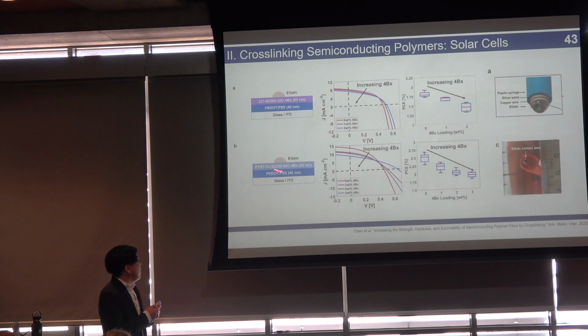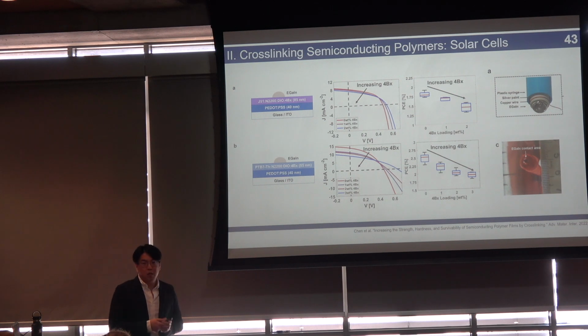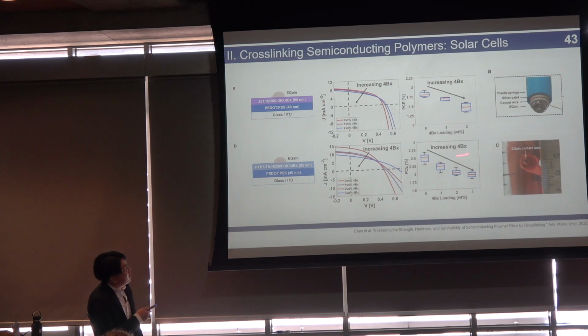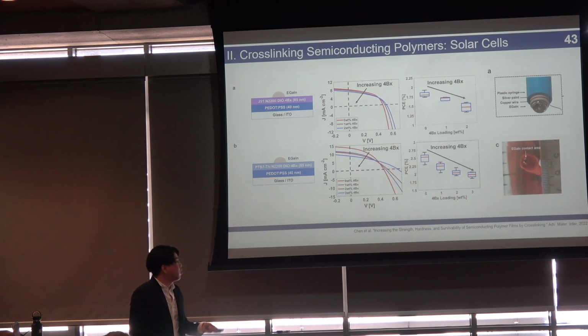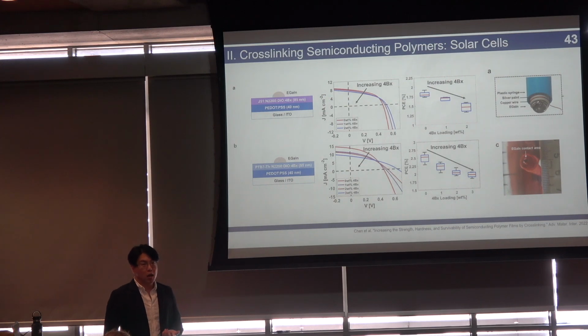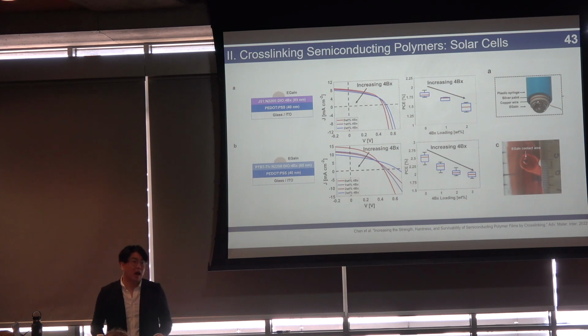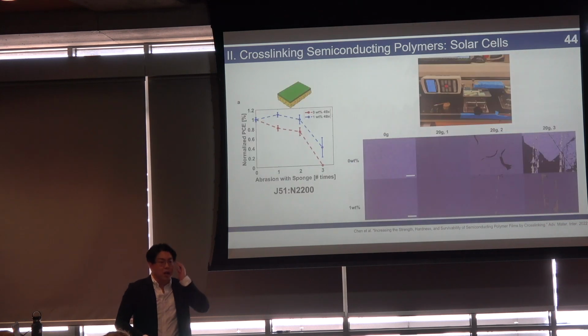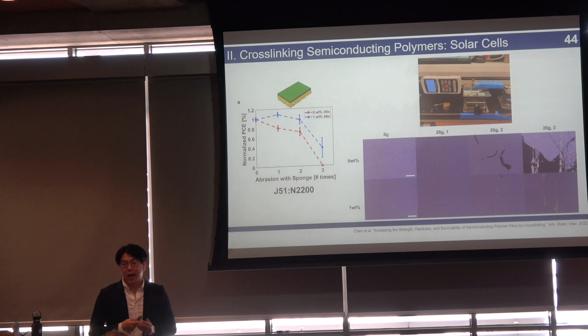Instead of putting on an evaporated top contact and a transport layer, we used an eGaIn liquid metal electrode to directly probe what's happening in our bulk heterojunction. And unfortunately, we do see that as we increase the amount of cross-linking we add, we decrease the electronic performance. So the question becomes, if we have this decrease in performance, what do we get out of this? And the answer is we can make use of the mechanical robustness.